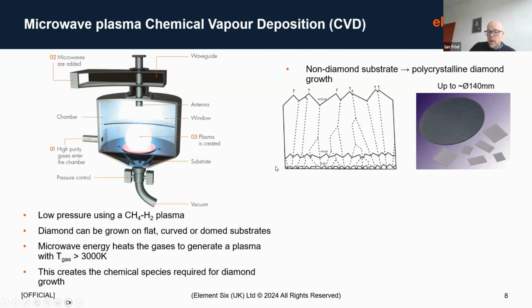In essence, there are 2 types of diamond that you can grow using this technique from the perspective of the microstructure of the material. Generally, if you grow on non-diamond substrates, you produce polycrystalline diamond. That's what's illustrated in this diagram here. So essentially, we nucleate randomly oriented grains on a substrate. Then you have competitive grain growth, and you form a fully dense wafer, which is comprised of diamond crystallites. And that's a great material for addressing the majority of industrial applications that we make. You can produce large areas up to around 140 millimeter wafers in diameter. And they're essentially just limited by the size of the reactor and the size of the substrate that you use.